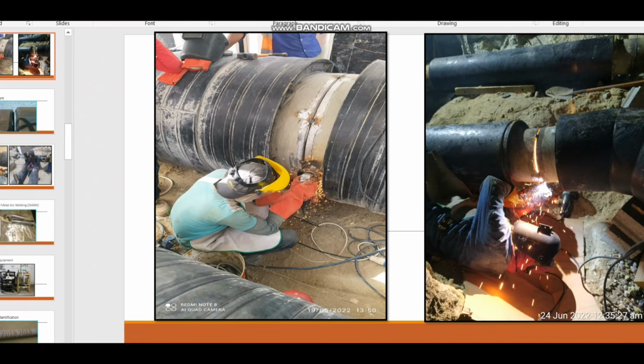And not only that, for example let's say you are doing the welding from top to bottom like this, and you have kept the root gap as 3 mm. What will happen when you are welding from the top side, because of the heat on the bottom side, the two pipe materials will undergo shrinkage and compression. So if you have kept 3 mm here, surely when you weld from the top side, because of the heat, this 3 mm will be reduced to 2.5 mm, 2.4 mm. That is another reason. So this root gap we normally keep 3 to 4 mm, slightly higher. 4 mm also is a perfect way to keep the root gap.